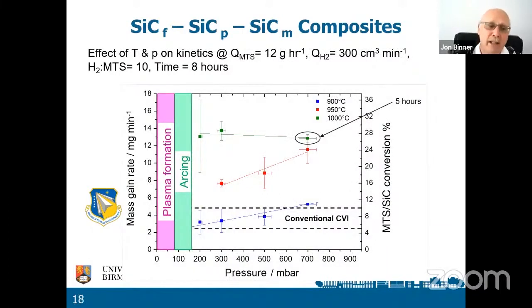And then we can check the rates. So on this plot, on the left-hand axis, you have the mass gain rate, and the bottom axis is the pressure of the system. You can't operate at very, very low pressures because you get plasma discharge. If you operate at slightly higher pressures, you encourage arcing, but anything above about 150 millibars, we can operate successfully. And then you've got the plots at 900, which is roughly equivalent in deposition rate to conventional CVI. If you move to 950, you get faster deposition. And if you move to 1000, you get faster still.